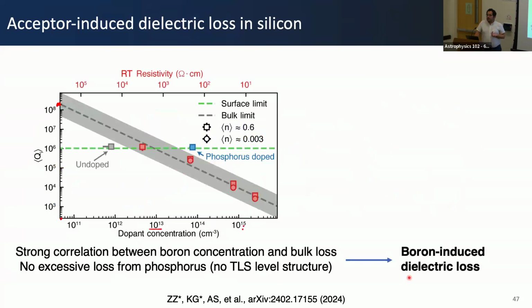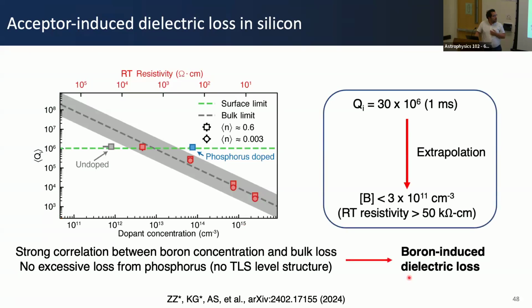And then we repeated these experiments for different concentrations of boron in different wafers. So we basically purchased several float zone wafers with different boron concentrations. And here I'm plotting the internal quality factor of resonators as a function of the boron concentration. And we see a very clear correlation. So we think that with all this evidence, we can conclude both from the theory and experimental evidence that borons are acting as a TLS bath for superconducting circuits.